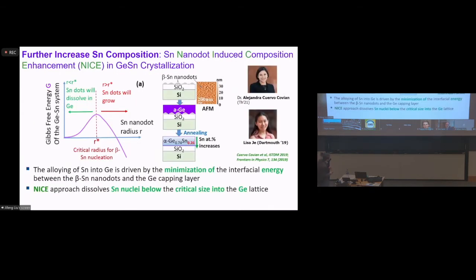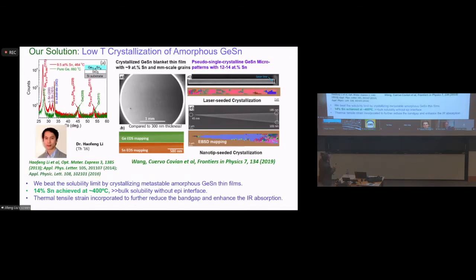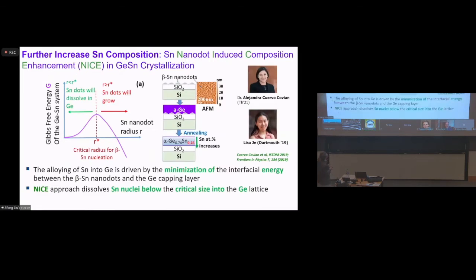And you may want to ask, can I further increase that composition? You get about 14% in this direct crystallization approach. That's pretty good. But if you want to push the detection to even longer wavelengths, you probably need more tin. And that's exactly true. So we try another trick right here. What you worry about in this material is that when you heat up the film, the tin is going to segregate, right?